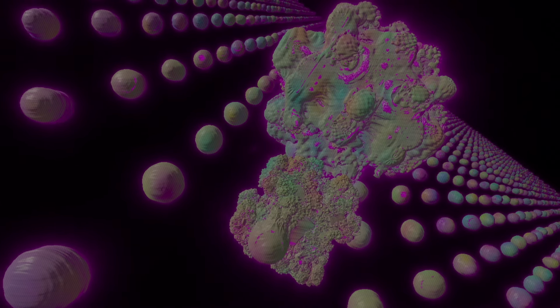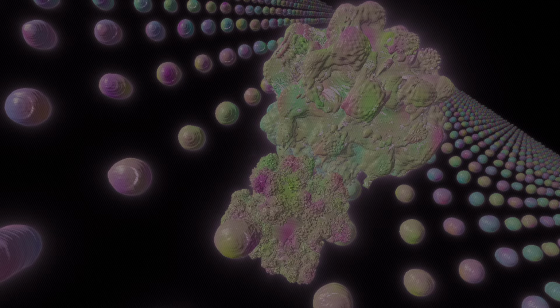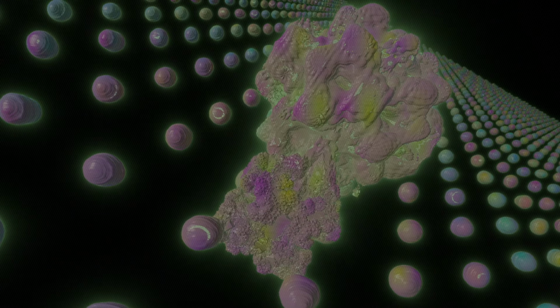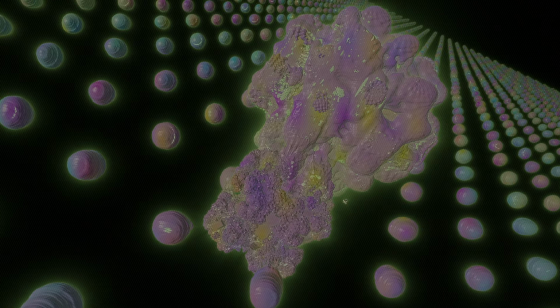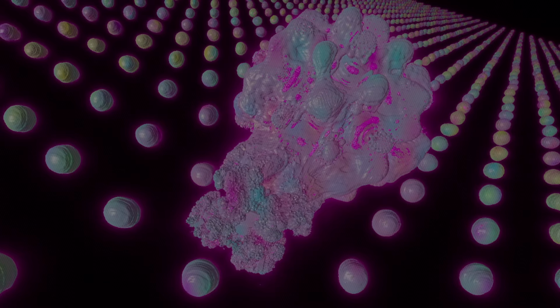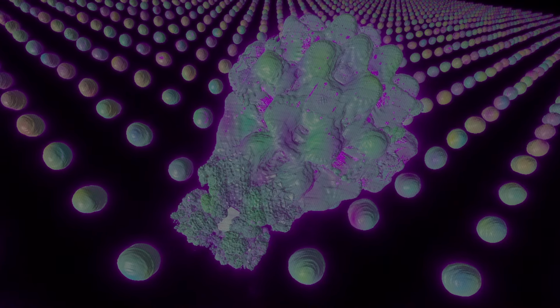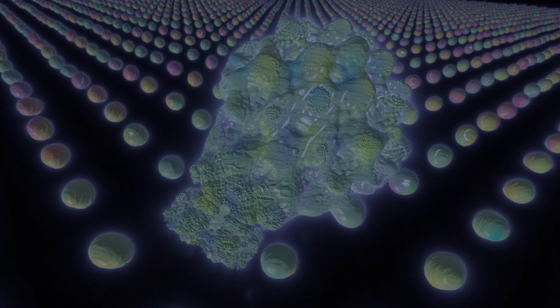Right. And there are different flavors. Raman scattering typically uses visible or near-IR light. It's primarily sensitive to optical phonons, usually right near the Brillouin zone center, because photons don't carry much momentum compared to phonons. Raman is great for identifying specific vibrational modes, like a chemical fingerprint, and determining crystal symmetry. It requires the vibration to change the material's polarizability. Okay, so Raman for optical modes.